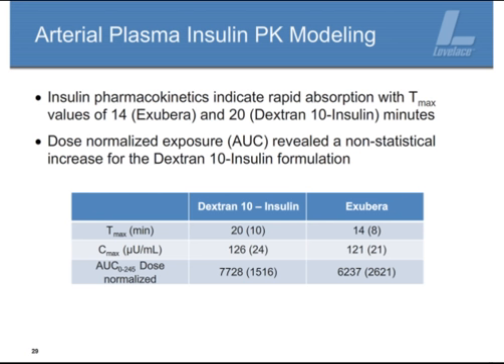Reflecting back on that concentration time profile for the arterial plasma insulin, I talked about the fact that the Dextran formulation, the Bend Research formulation, had a slight tendency to an increased concentration throughout those middle time points. That's also reflected in the area under the curve, as you see on the bottom line of the table. You see a little bit of a tendency for the AUC to be higher for the dextran formulation when compared to the Exubera. However, as I noted earlier, that was determined not to be statistically significant.